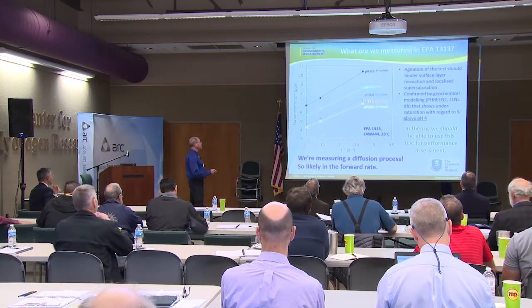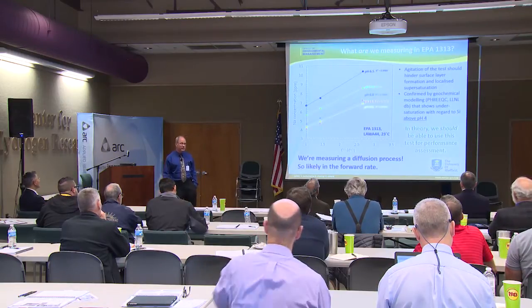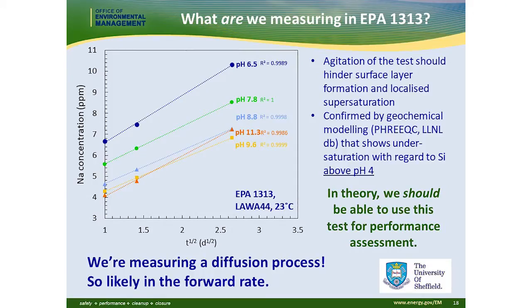Then when we take a look at the 1313 measurements and we look at this as a function of pH, these are the endpoint pHs with it, and we look at the 1313 as a function of time, we see we have a diffusion controlled reaction, that it falls on that straight line when we look at a t to the 1/2 plot. So that also seems reasonable.